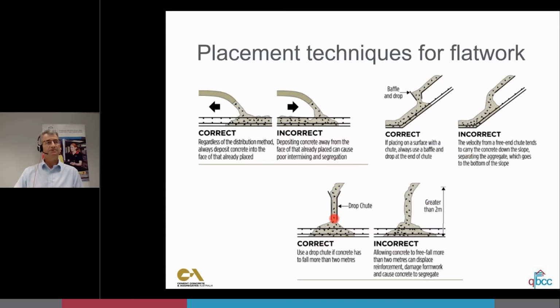Down here, we've got a drop chute, and the drop chute is pretty close to the existing concrete. So that's preventing this greater than 2 meter free fall that you see on this next picture. So if you let concrete fall for greater than 2 meters, it'll have the risk of causing the concrete to segregate, depending on the nature of the concrete and what the slump or the spread value is.